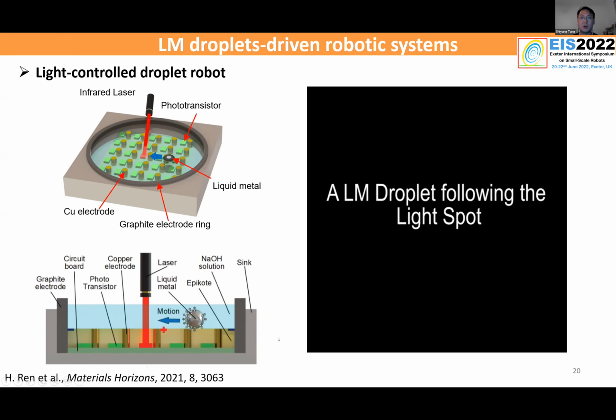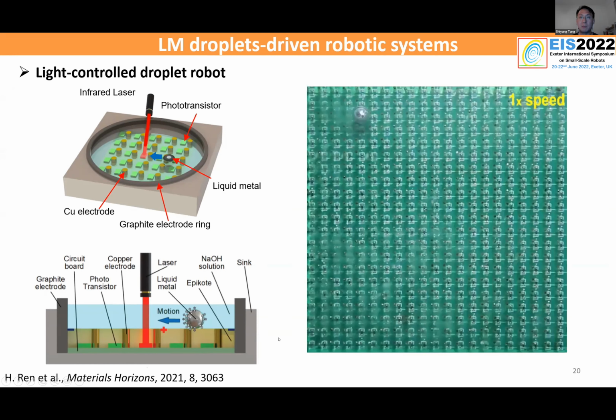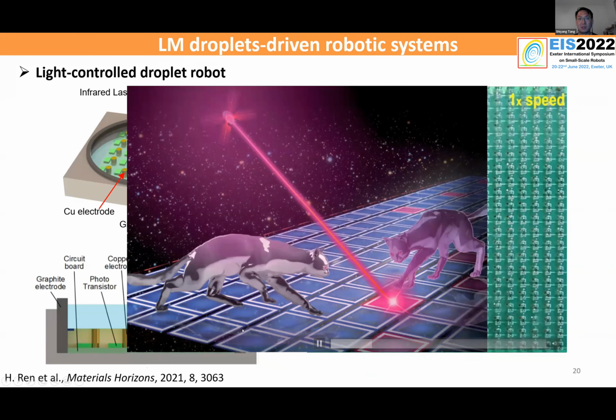So this footage shows that the droplet is able to follow the position of the laser spot. Here we used red light to show it. Actually, in the real experiment, we use infrared, so we're not going to interfere with the vision. Using this method, we created what we call a liquid metal cat, because cats are always obsessed with laser light.